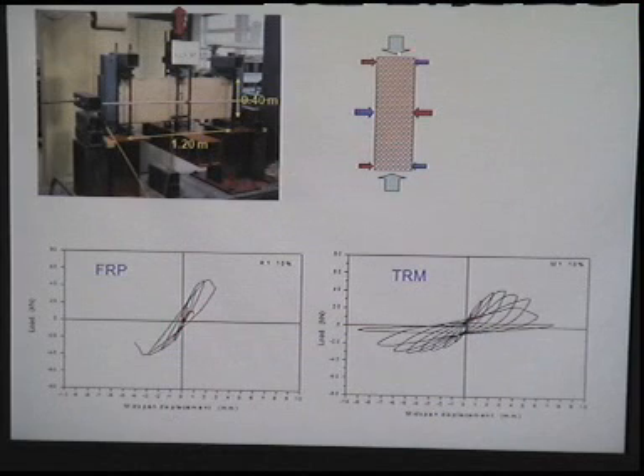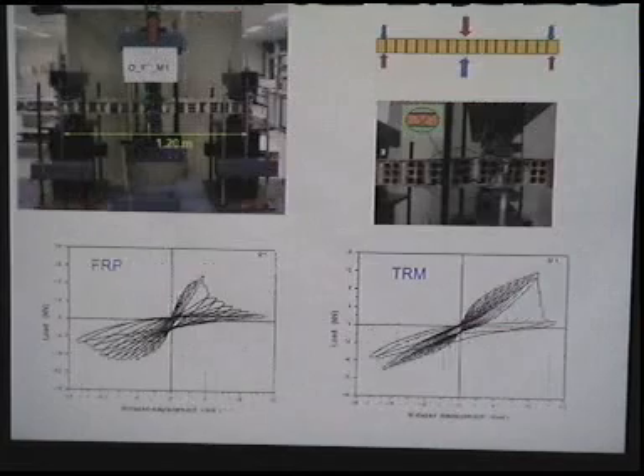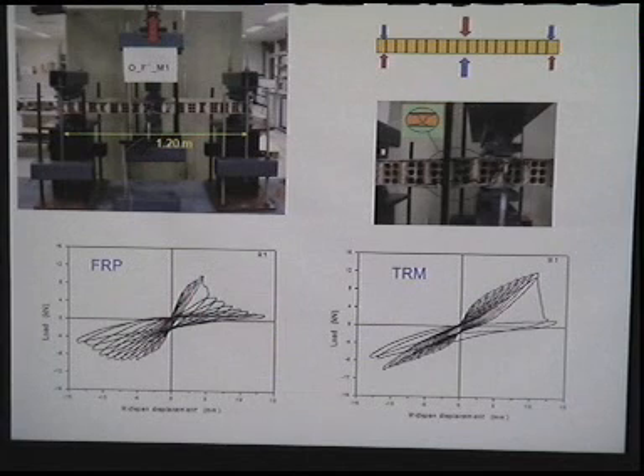When we look at different types of structural elements, that is column-type structural elements with an axial load and cyclic bending and shear, again, red is the rather poor response of the control, that is the unstrengthened wall, and then you see how the strength increases if we use the FRP, and what happens for the case of the TRM. Here we have a dramatic increase in the ductility also. Masonry subjected to out of plane, again, our strength is practically zero here in the absence of axial force, but we have a very high capacity if we strengthen the system with the FRP or the TRM.